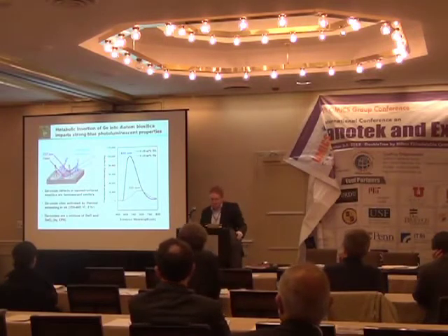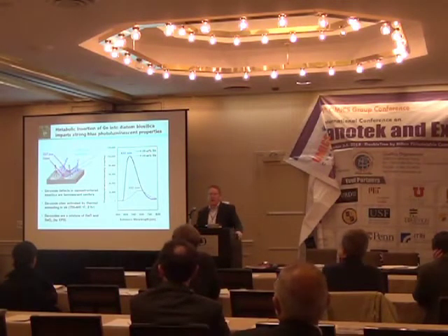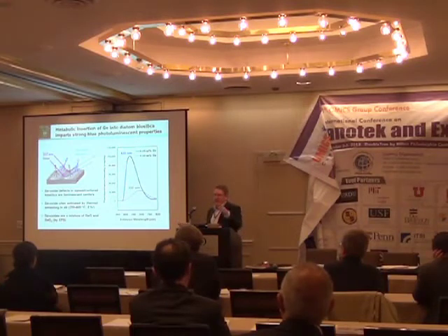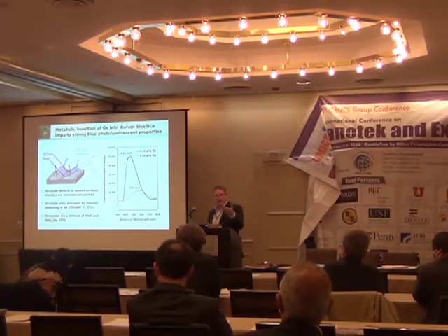Now, what we found is that when we put this material into the diatom shell, we enable the photoluminescent property to the material. The actual native biosilica itself has some level of photoluminescence due to the fact that it is a biogenic material. This biogenic material has silanol groups that impart some photoluminescence to the material. In our particular analysis, we just used a 337 nanometer UV laser to excite the material, and then just looked at the emission from that material.